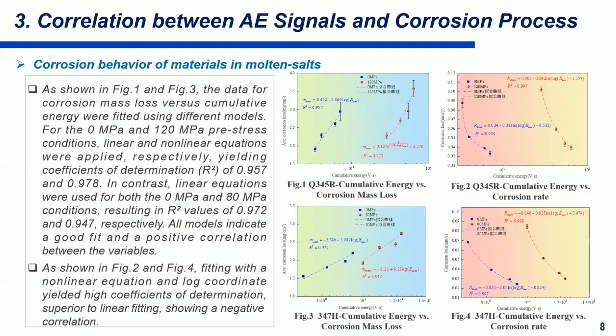Wagner's oxidation theory. As shown in Figure 1 and Figure 3, the data for corrosion mass loss versus cumulative energy were fitted using different models. For the 0 megapascal and 120 megapascal pre-stress conditions, linear and nonlinear equations were applied respectively, yielding coefficients of determination of 0.957 and 0.978. In contrast, linear equations were used for both the 0 megapascal and 80 megapascal conditions, resulting in R square values of 0.972 and 0.947 respectively. All models indicate a good fit and positive correlation between the variables.